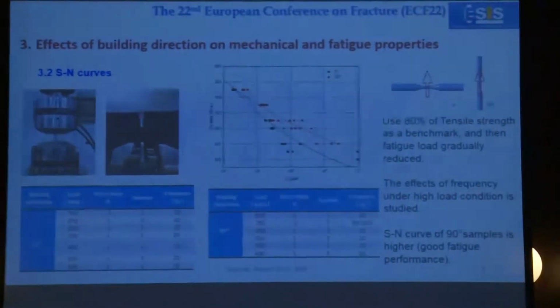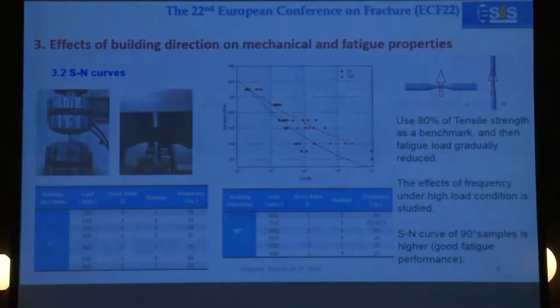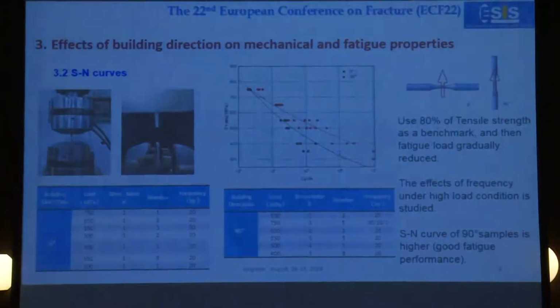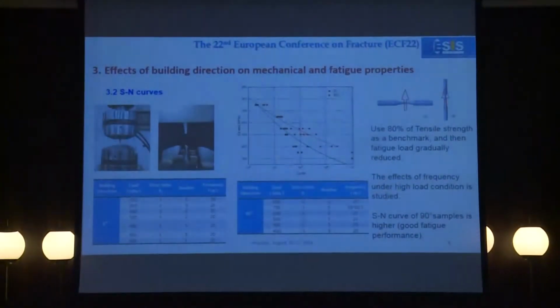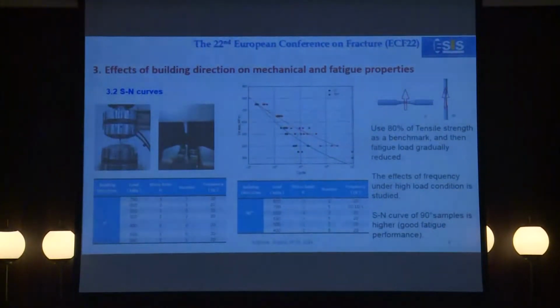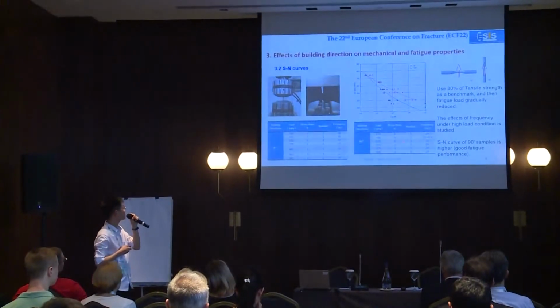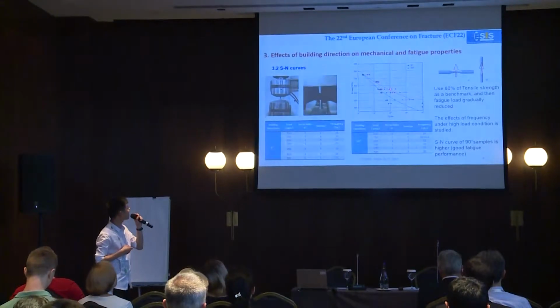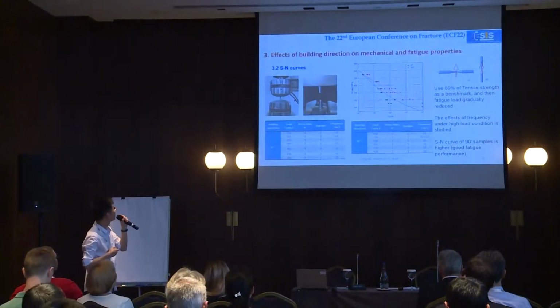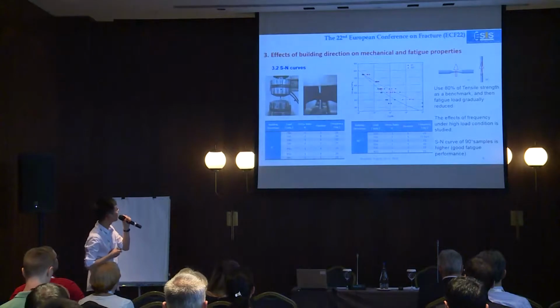And then we performed the fatigue test. We used 80% of tensile stress as a benchmark, and then the fatigue load gradually reduced, and the details are shown in these 2 tables. In these load conditions, the effect of frequency is studied. From the SN curves, we can get that the 90-degree samples have a good fatigue performance.